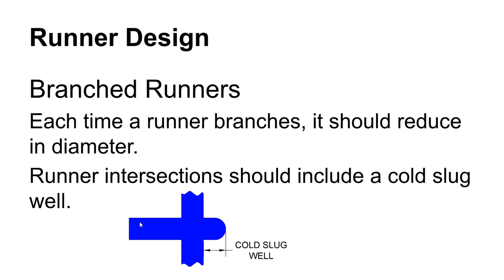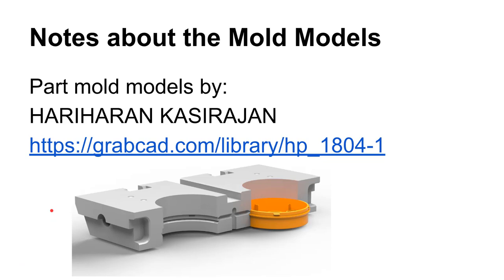A really common feature you'll see everywhere is the cold slug well. As plastic flows through the runner, it kind of cools and skins over on the front surface as it moves. When it reaches a cold slug well, that semi-solidified front of material — instead of going into the cavity — gets captured in the cold slug well, and then new fresh plastic branches off. At these branches you have an opportunity to get rid of that old skinned-over front of plastic and refresh it with a nice new front as it moves through the runners.